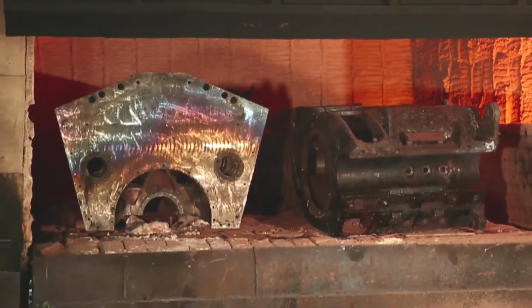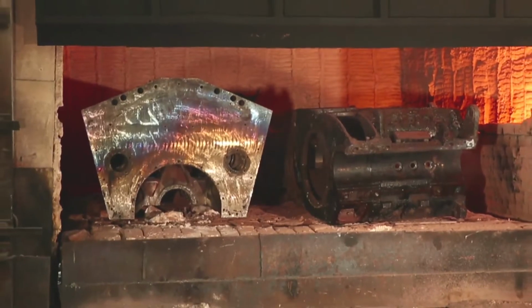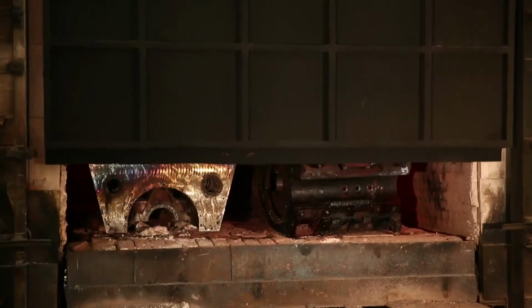After that, cooling starts at the rate of 70 to 80 degrees centigrade per hour with door closed till temperature reduces to 200 degrees centigrade. Thereafter, the door is opened and components are allowed to cool in air for machining.